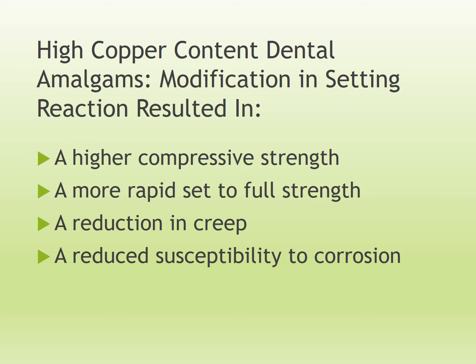This modification in the setting reaction of the dental amalgams resulted in a higher compressive strength, a more rapid set to full strength, a reduction in creep, and a reduced susceptibility to corrosion.